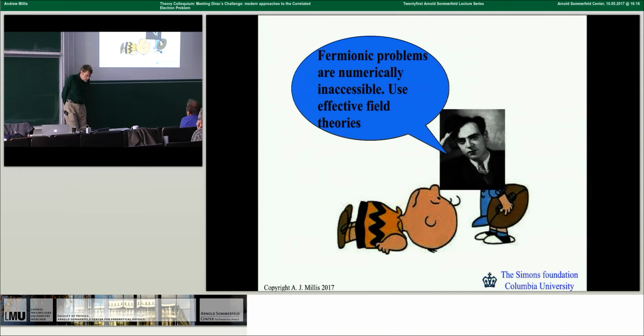So you put your finger on one of the big weaknesses of these theoretical techniques, all right? And that is that while we can calculate the temperature dependence of the energy, getting the entropy, we can't get the entropy directly, or the free energy directly. So to get the entropy, what you have to do is start from a known configuration and compute the energy very accurately as a function of T, and then take the internal energy and take the derivative, all right? And that's more work than basically we've been prepared to do to pin down exactly what's happening at the transition, or even at higher temperatures where there are interesting questions of making connections to cold atoms, right? But it's essentially a matter of laziness.